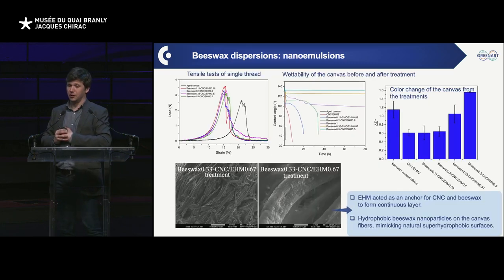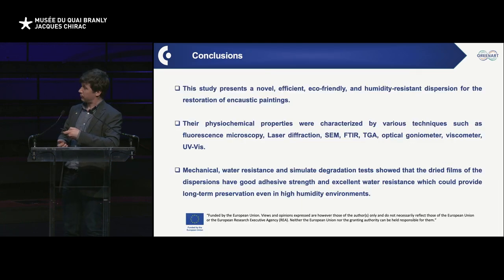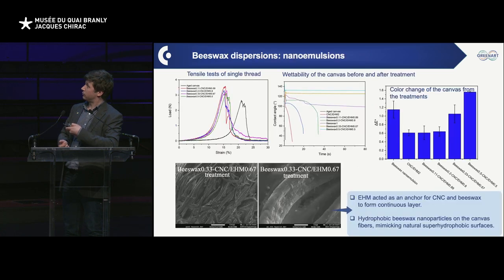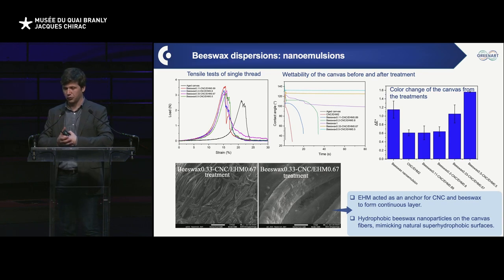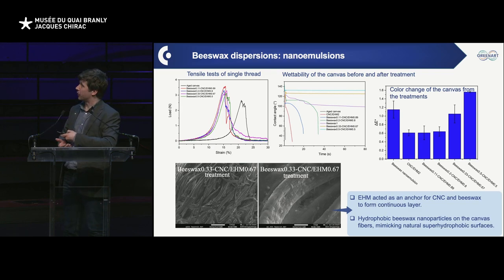Bottom line, and quickly here, we thought, okay, this is a very nice system, but we can use it for canvases, for instance, because canvases have been historically treated with wax. And here, maybe we can do something about wax. So we took some regular canvases threads. We did an accelerated aging. So basically, this is the result of the accelerated aging. We decompose the cotton in order to make it weaker. And then we apply our nano emulsion onto it, simply a spraying and so on.